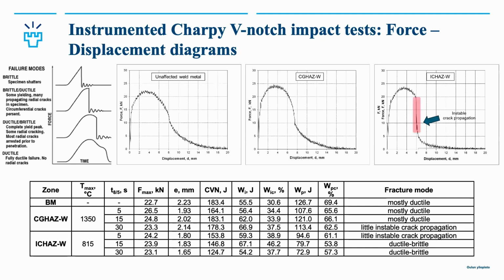And then with this instrumented Charpy V, in addition to the absorbed energy, we also see other data. We can have force displacement diagrams, and we can see the fraction of energy that went for initiation of the crack and that went for propagation of the crack. And from these graphs we can read the failure mode, whether it's completely ductile or partly ductile. For example, here in the unaffected weld metal, this looks very ductile, so it is similar to this. While for example here in the intercritical heat affected zone, we see some unstable crack propagation here.